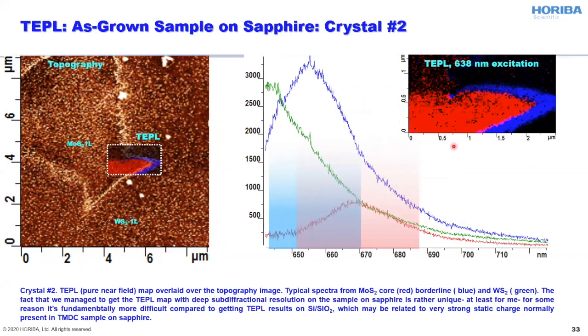really well why it's so difficult to do on sapphire, because on silicon dioxide, it's quite a conventional measurement, and we have a number of beautiful results on tip-enhanced PL imaging of different structures, including lateral heterostructures. But when these structures are grown on sapphire, for some reason the measurements become very complicated. Probably it has something to do with the fact that quite often sapphire holds a lot of static charge, and that may affect either doping or may affect somehow the tip-enhanced photoluminescence imaging itself.